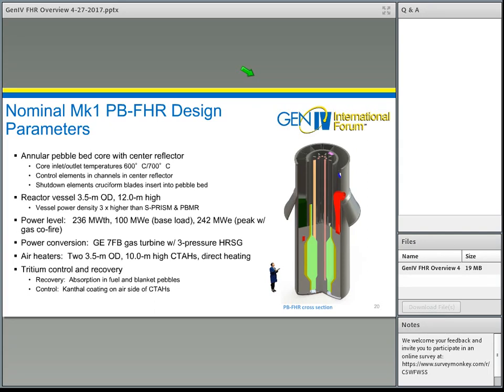The core is actually a pebble bed core, and in FHRs, because the fuel has lower density than the salt, these pebbles actually float, which means that one is going to defuel the pebbles from the top of the reactor, and pebbles are injected into the bottom of the core and then circulate upward. Typical residence time, just like pebble bed helium-cooled reactors, will be about 30 days.